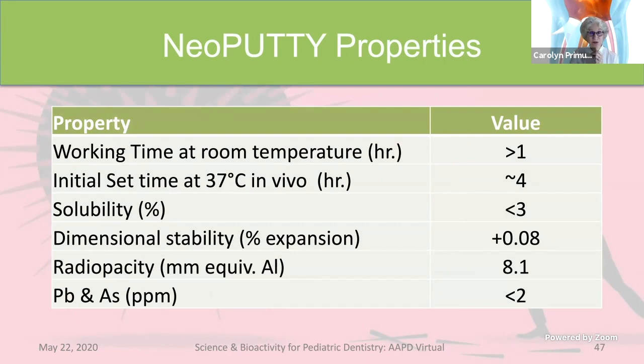You may be asking, what are the properties of Neo-Putty? Now, this is important to think about because it's a ceramic powder that is suspended in an organic liquid. Because it doesn't have water and you're not mixing it with water, it has a longer working time at room temperature after you dispense it. But it needs water from the body to set.